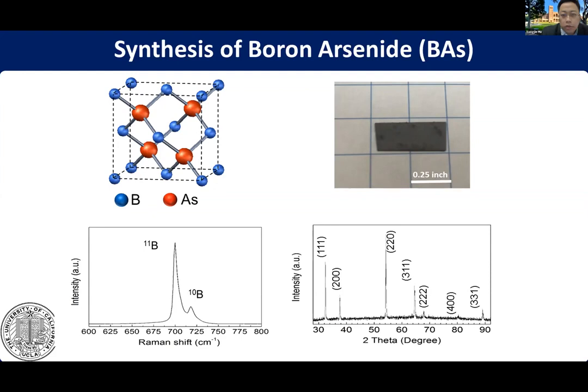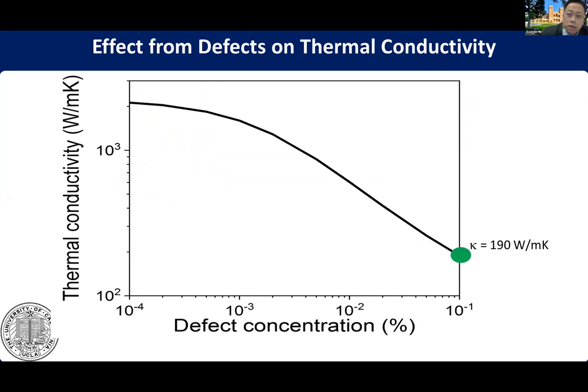So we did preliminary synthesis. We made inch-size thin film of boron arsenide and verified the crystal structure with Raman spectroscopy and XRD. And also we did initial thermal measurement using ultrafast pump probe spectroscopy. The measurement of the initial sample gave a thermal conductivity value around 190 watt per meter Kelvin, which is already higher than silicon, but still much lower than the theoretical expectations.